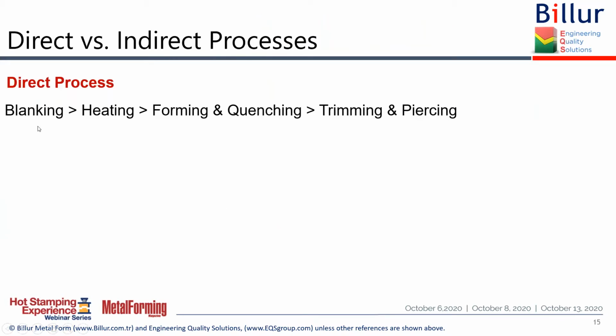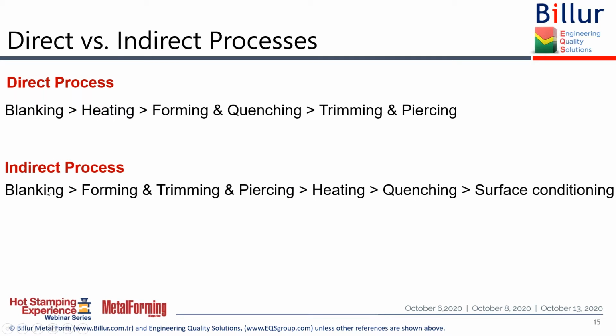Now, when I put these 5 operations in order, in the direct process, we have blanking, then we heat the undeformed blank, we form and immediately quench it, and then we take it to laser trim and pierce typically. In the indirect process, we blank and cold form, then we do the trimmings and piercings as well. Then we heat the already formed and pierced part, quench it, and in most cases we need to do a surface conditioning, which could be sandblasting or similar.